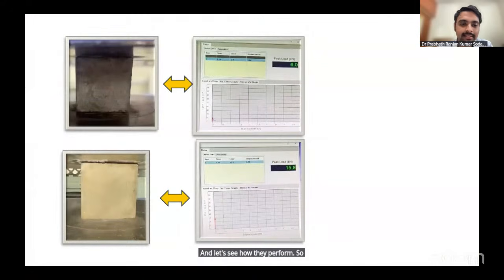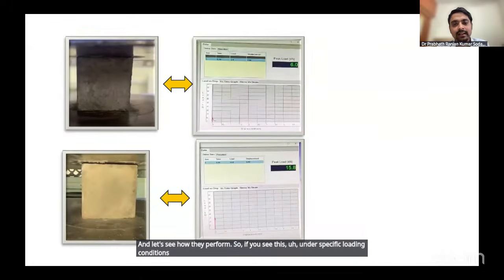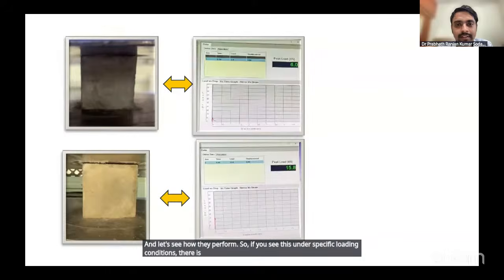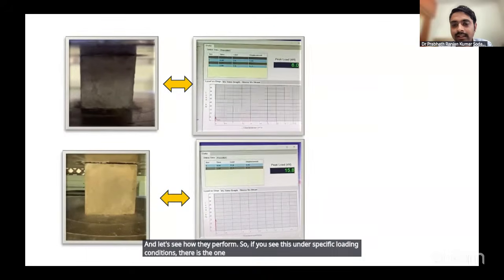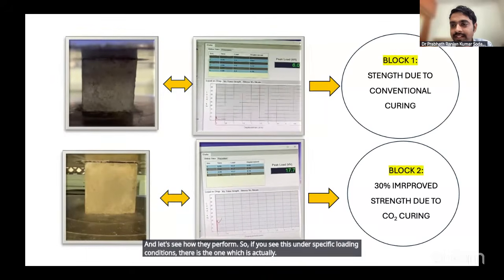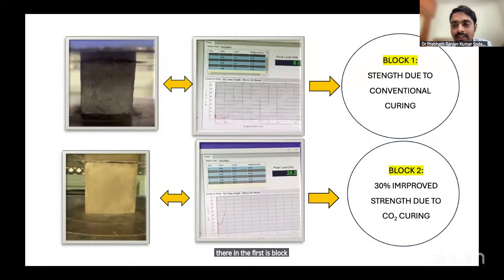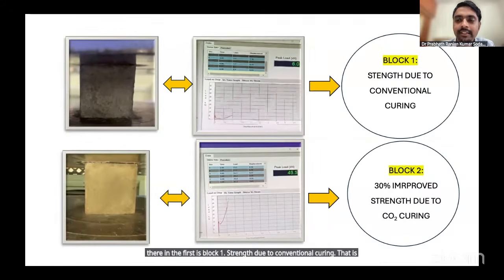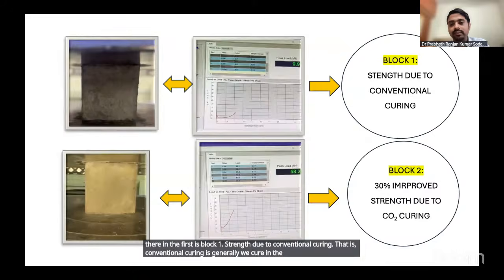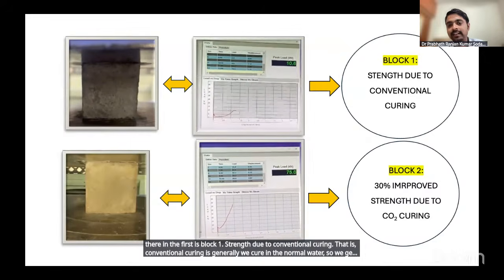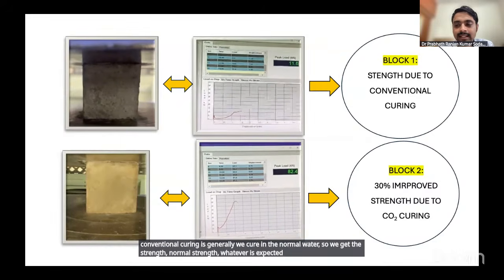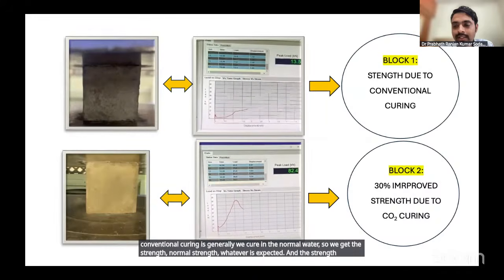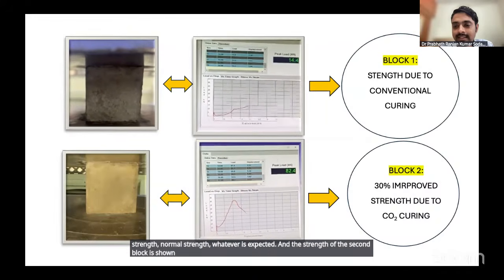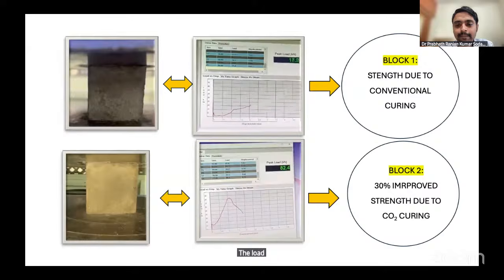So if you see, under specific loading conditions, the first one is block 1, strength due to conventional curing. That is, conventional curing is generally where we cure in normal water. So we get the normal strength, whatever is expected. And the second block shows a 30% hike in the strength, the load carrying.